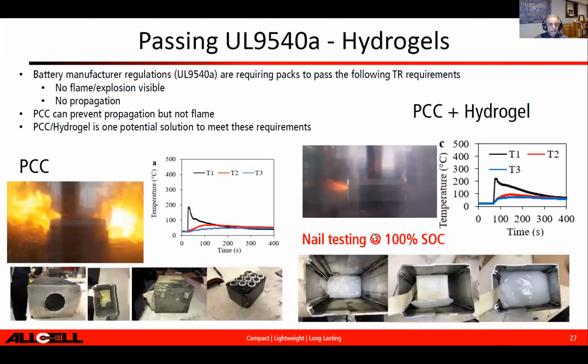I want to talk to you a little bit about another issue that we've seen, once you stop thermal runaway propagation, which is the flame issue from the electrolyte. And this is something that has been addressed by the industry. Basically, when a cell fails, even if you stop thermal runaway propagation, that flame that comes out of the cell, if it escapes the pack, it could cause fire for the surrounding pack surroundings.